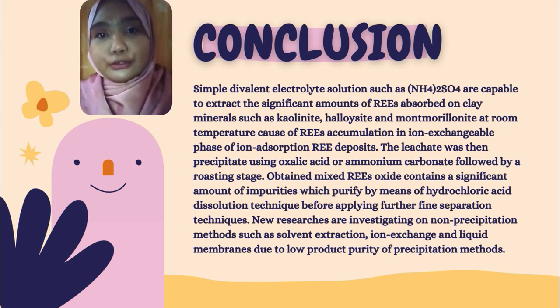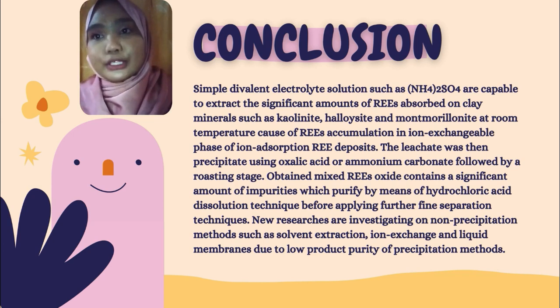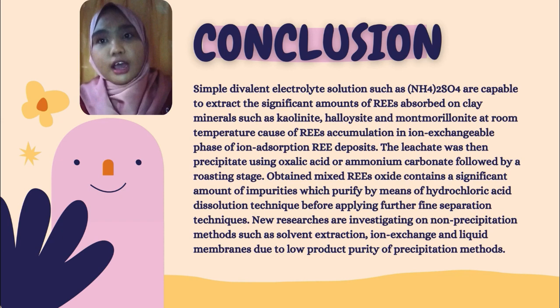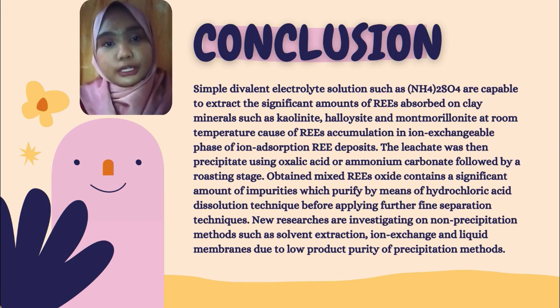In conclusion, simple divalent electrolyte solutions such as ammonium sulfate, (NH4)2SO4, are capable to extract the significant amounts of REEs absorbed on clay minerals such as kaolinite, halloysite and montmorillonite at room temperature, because of REEs accumulation in ion exchangeable phase of ion adsorption REE deposit.